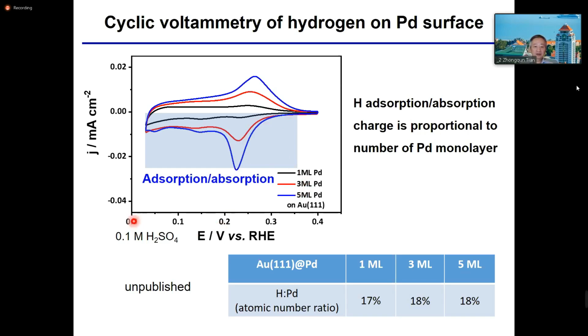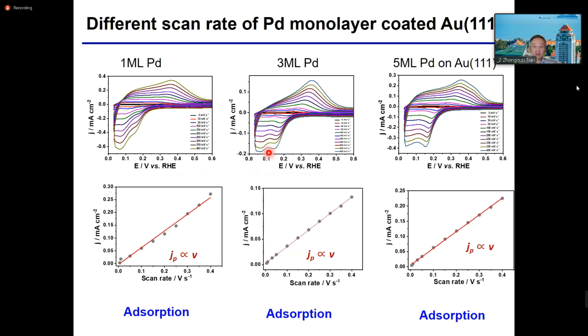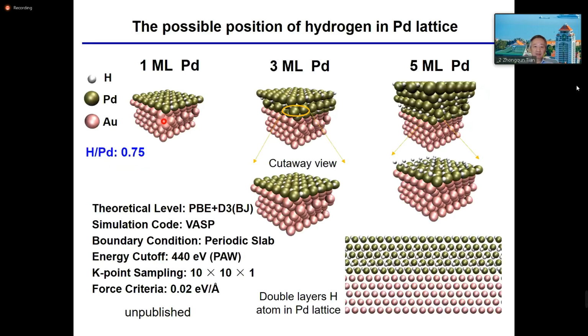Please notice that the hydrogen evolution will take place here, so the current will be huge here. However, here we can carefully design some hydrogen or deuterium adsorption and absorption. We can also calculate and find that the adsorption step is the rate control step instead of absorption, because absorption is huge.